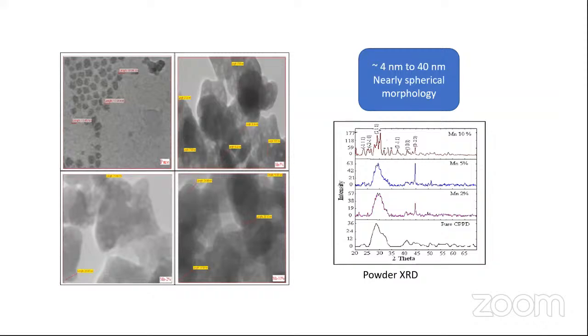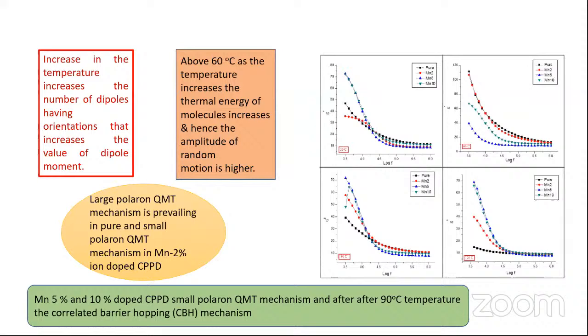The increase in temperature increases the number of dipoles having orientation, which increases the value of the dipole moment. So as temperature increases, the dielectric constant increases. From Jonscher's power law, the large polaron quantum mechanical tunneling mechanism is prevalent in pure CPPD, and a small polaron quantum mechanical tunneling mechanism is prevailing in manganese 2% doped CPPD. Again, in 5% and 10% doped CPPD, the quantum mechanical tunneling mechanism is prevailing, and after 90 degrees Celsius, the CBH mechanism is prevailing. So depending upon the temperature, two types of mechanisms are prevailing.